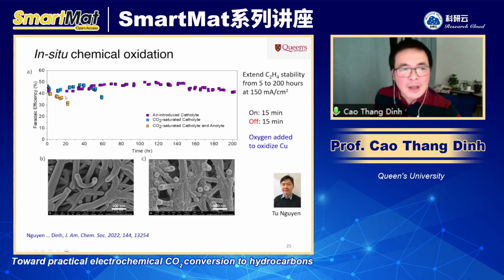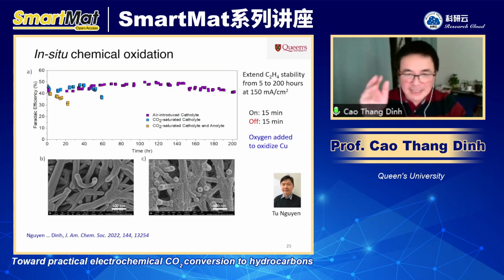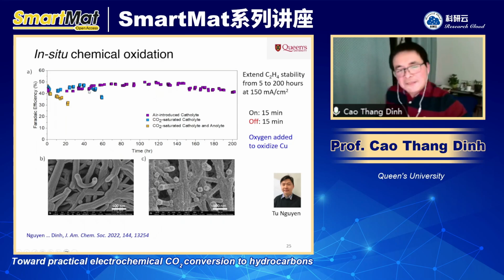So if you look at this graph, when we do not have any oxygen in the system, so we bubble the CO2 in the cathode and in the anode so that we remove all of the oxygen, the system is stable for only about 20 hours, right? Now, if you only remove the oxygen in the cathode, so you still have some oxygen in the anode that can migrate to the cathode, so you still have a little bit of oxygen in the system, you can run the reaction for about 50 hours. And if you control the amount of oxygen inside the cathode, so that you have enough oxygen to oxidize the surface, you can run the reaction for 200 hours.